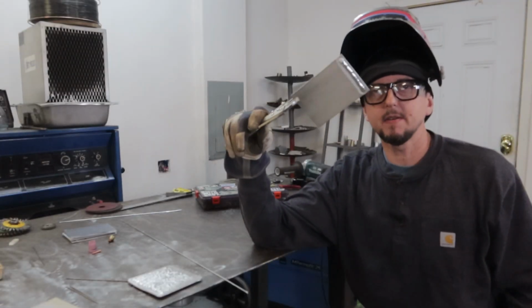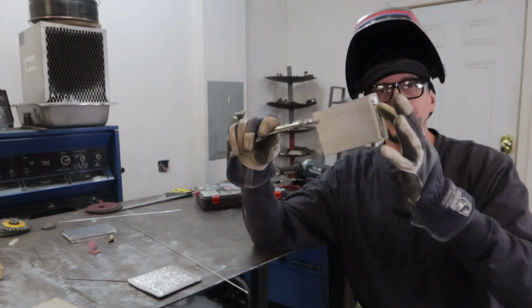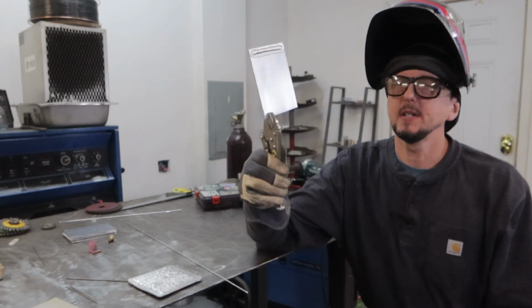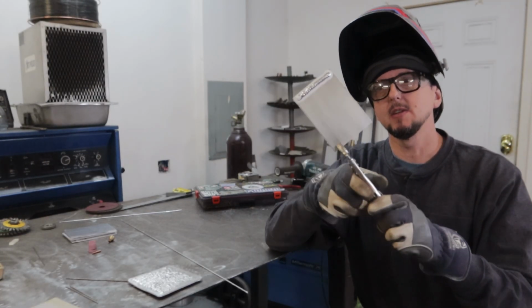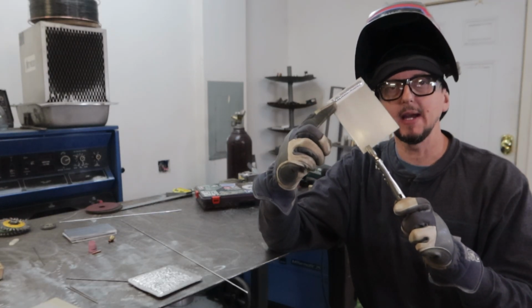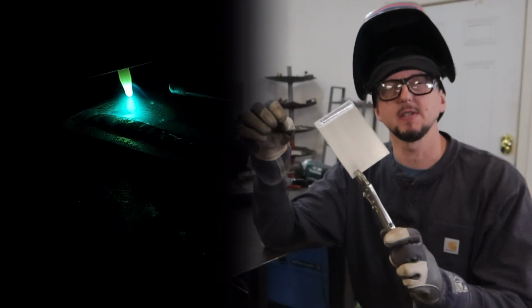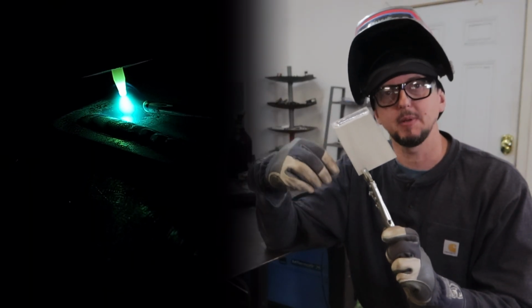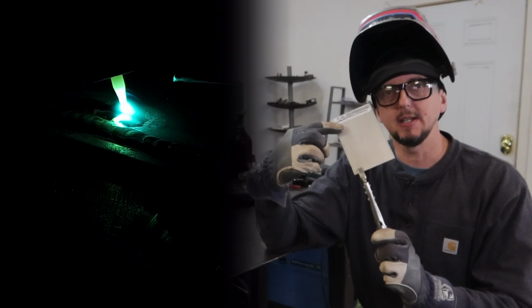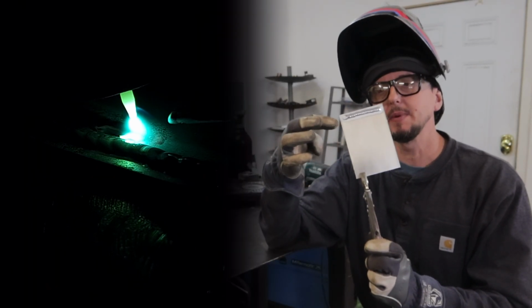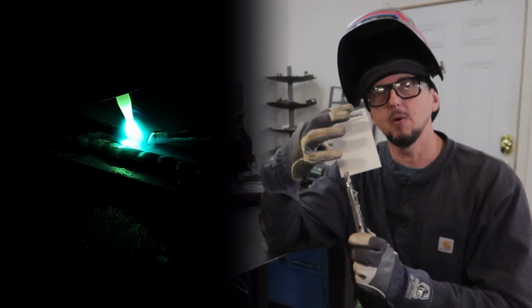All right, so we have our first pass on, our first bead, right? And now we're going to start overlapping the beads. So we're going to put our second bead right next to it, but we want it to overlap by maybe 1/16 of an inch or something like that to actually surface the plate. So we don't want any space in between. So we're going to put the next bead right next to it and overlap that toe. And we're being careful not to go all the way to the edge, all the way around.